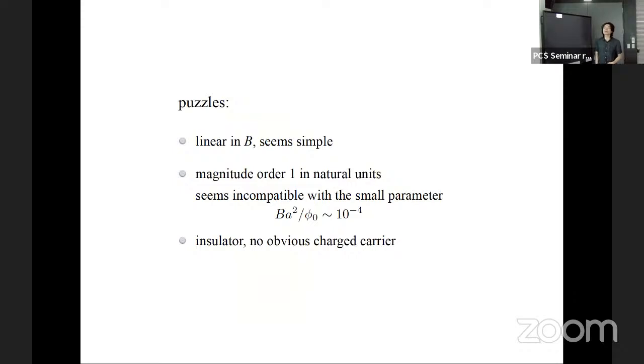Right. So let me summarize a little bit. The puzzle is this. The effect is linear in the magnetic field, so it seems it should be very simple to analyze. But the magnitude is order 1 in natural units, which seems incompatible with the small parameter Ba squared over phi naught, which is of order 10 to the minus 4. So that seems very weird. And also, this is an insulator. There's no obvious charge carrier that can couple to the magnetic field. As we just said, phonons are neutral, but if you have an ionic crystal, the phonon motion can involve some motion of the sodium and the chloride ions, but that effect is way smaller than this, right? So these are the puzzles.